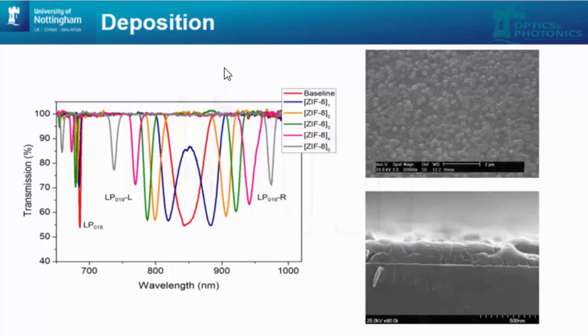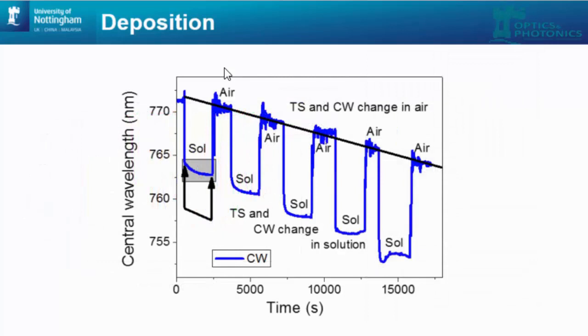Advantage of optical fibers: you can measure your deposition in real time, so you can optimize the response of your sensor simply by stopping it at the right time when you have the right thickness and the right optical range. Which is shown in here, for instance. So you can see in solution when the fiber is immersed into the film forming solution, you can see this change, wavelength shift in the attenuation band, and it is because of the growing of metal organic frameworks on the surface.